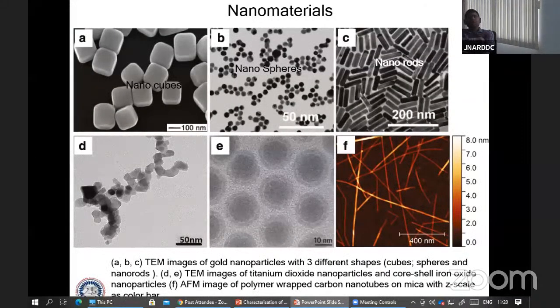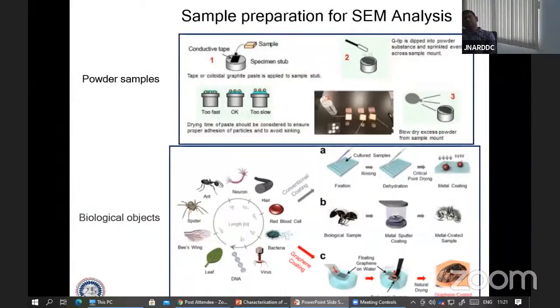Suppose you look at gold particles. These gold particles have different kinds of shapes like nanocubes, nanospheres, and nanorods. So these are the 3 different morphologies of gold nanoparticles. And if you look at titanium dioxide and the core shell iron oxide, we can see the nanoparticles here. And the last image is an AFM image of polymer-wrapped carbon nanotubes on mica. These are some of the examples of nanomaterials.